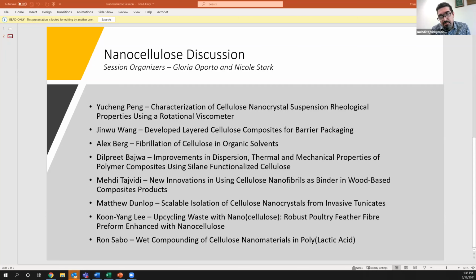Within that research, of course, the biggest issue was how to remove water from nanocellulose and from the system when you mix these together. We figured out a natural phenomenon that we now call contact dewatering as a way to remove a lot of water without any heat application. Basically, when nanoparticles of nanocellulose are in contact with a surface with high specific surface area, like small wood particles, the bound water in the nanocellulose turns into free water, and water is now free to be easily removed. That system helps you do a lot of different designs with the product.